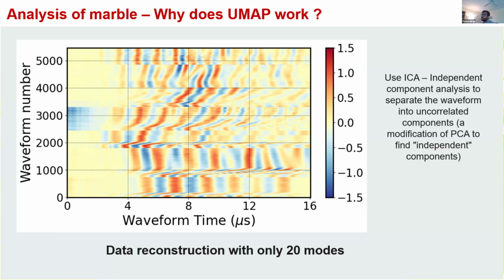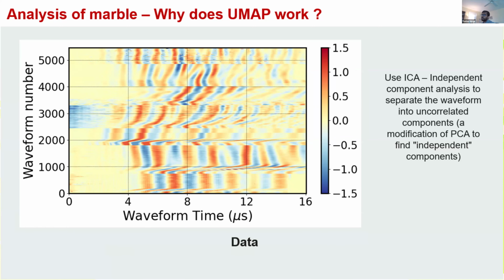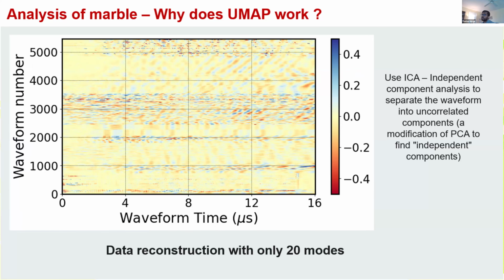So the scale of this is minus 1.5 to 1.5 normalized amplitudes. And then this is the error. So this is the difference between what the ICA predicts with 20 modes versus what's actually in all the data across different types of experiments. So that already starts to tell us, okay, there's not just lots of different types of processes occurring. There's only a few independent modes that we're seeing in different types of experiments, representing different types of damage mechanisms.